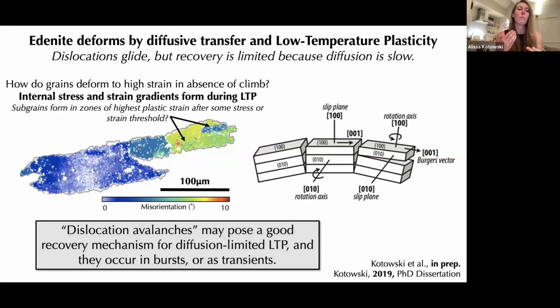So as a response to the generation of internal stress and strain gradients during this low temperature plasticity glide, one of the possible recovery mechanisms that might occur in response to this is something called a dislocation avalanche. This is a well-documented occurrence in the material science literature. And essentially, it might reflect dislocations tangling and then surpassing some critical stress or strain threshold, and then suddenly moving, suddenly recovering, suddenly cross-slipping, or leaving the grain. And so this, by definition, occurs in bursts or as transients. So what I propose is that the operation of this low temperature plasticity mechanism might actually be very important in explaining a potential grain scale mechanism that could produce naturally a slip transient.